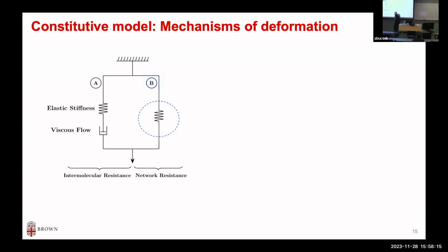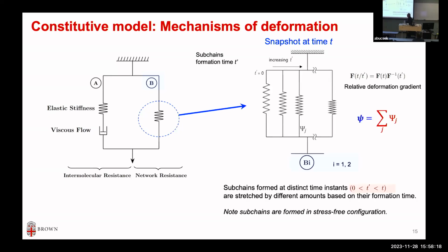B has two mechanisms. The physical picture is that each mechanism will have a bunch of series of springs together, because chains are breaking and forming. Depending on the time scale, from 0 to t, if you're looking at the behavior of the material from 0 to t, subchains are formed at t prime. So we have to only worry about the stress from t prime to t. A chain that started at 0 and deformed at t has a different behavior than a chain that was formed at a much later time, right? So we have to account for all these things. And the free energy, which is the mechanical response, will be a function of the summation of all these combined subchains for each of the mechanisms that we have to account for.